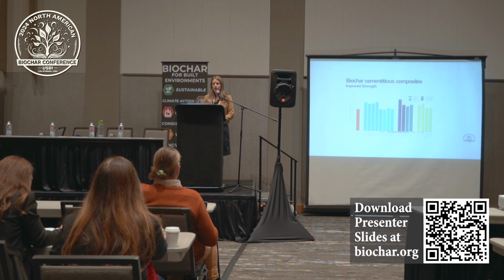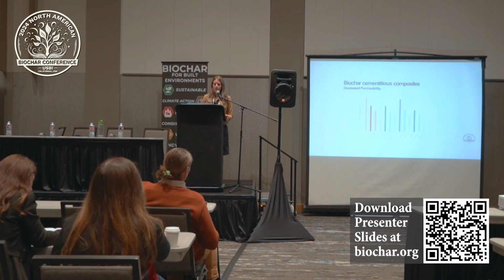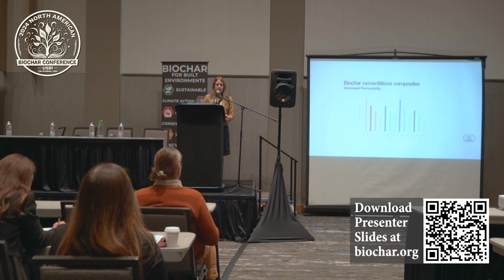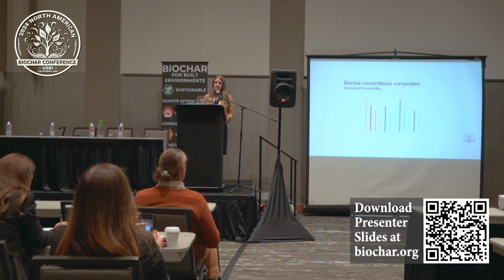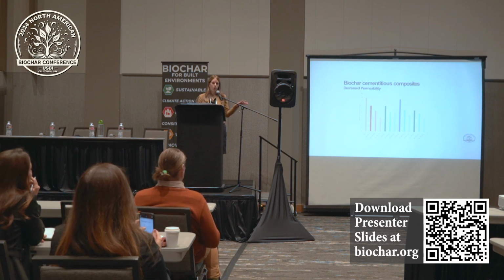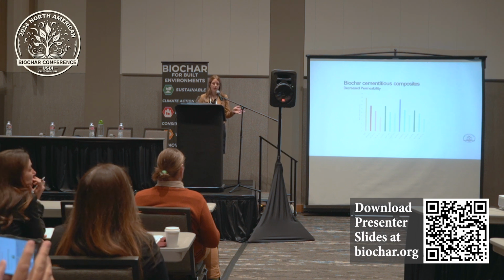We have demonstrated we can go up to 15 and even 20%. And most recently, I think we've tested up to 35% cement replacements with biochar, depending on the type of char and the mix design control. We've also recently been doing some permeability testing. So the way that we're measuring this is basically a measurement of the depth of water penetration when a sample is pressurized underwater and allowed under those conditions for 3 days.